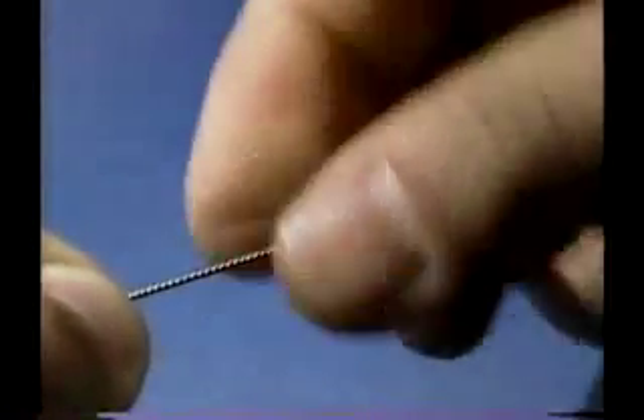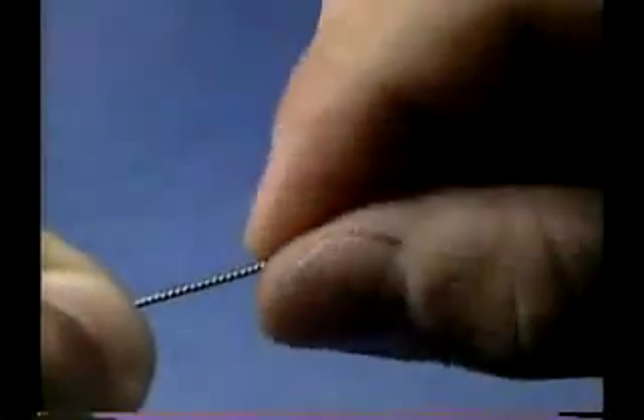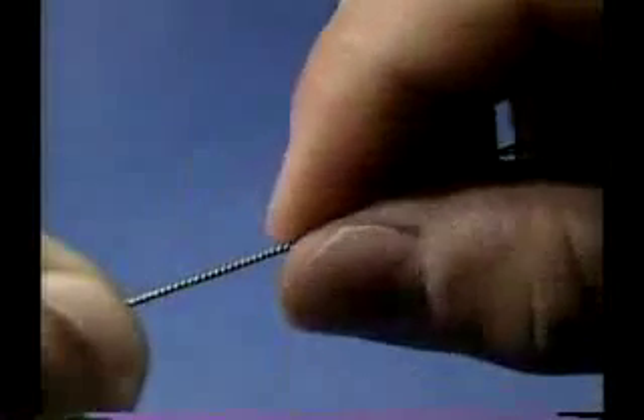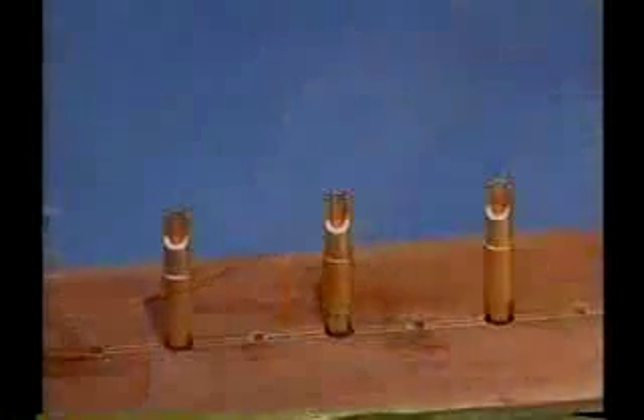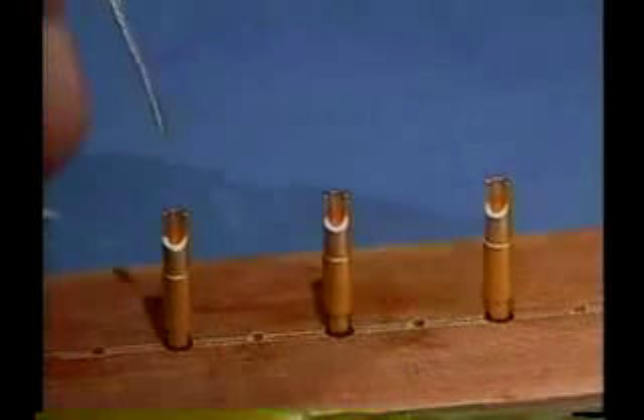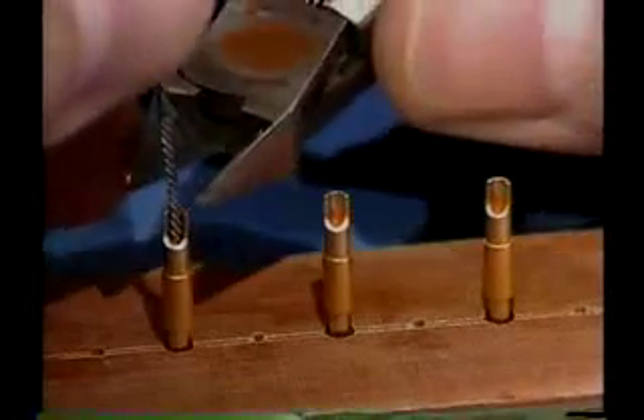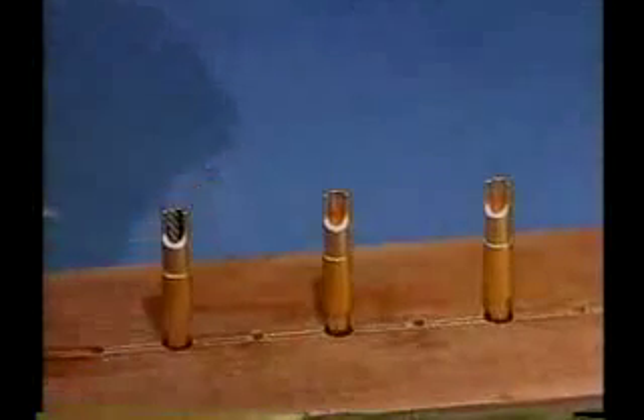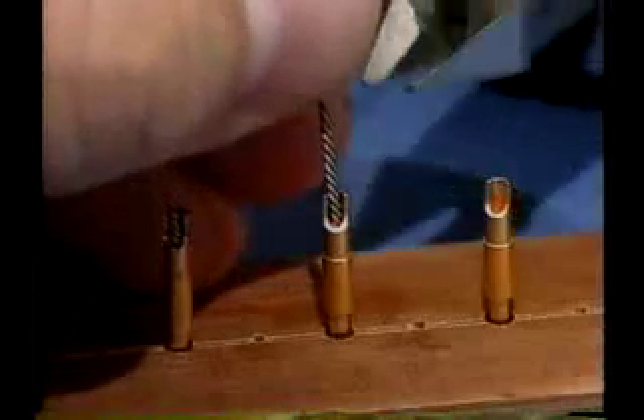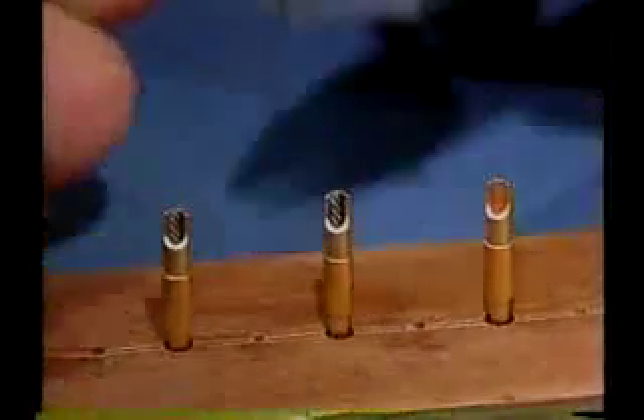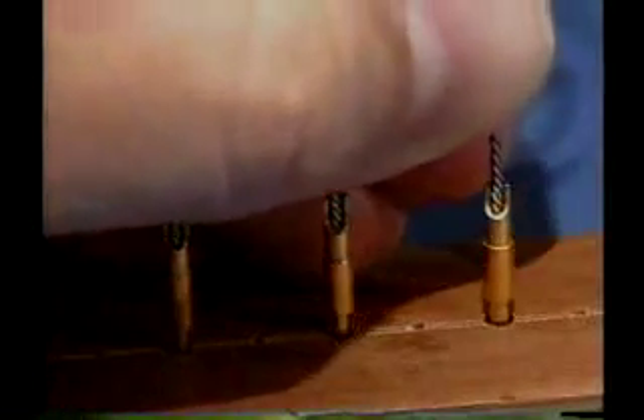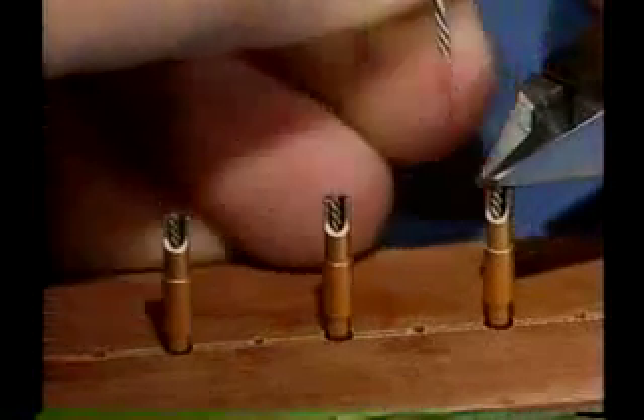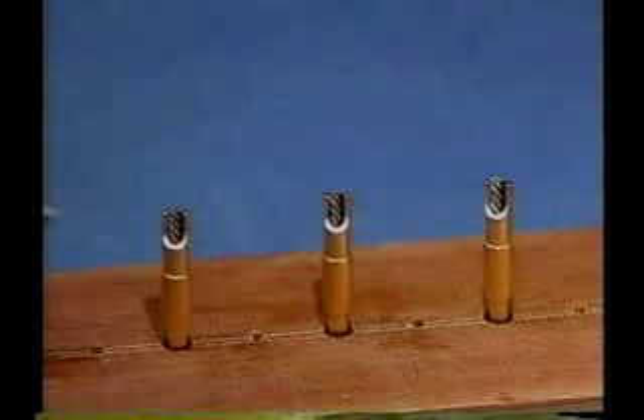Next, the cup should be filled with solder. Multiple strands of solder are twisted together tightly and inserted into the cup, or a single strand of heavier gauge solder can be used. This is called a solder pre-fill and should be cut off flush with the top of the terminal. This is done to avoid spilling solder on the outside of the cup. Different sizes of solder and the tightness of the twist can change the result.